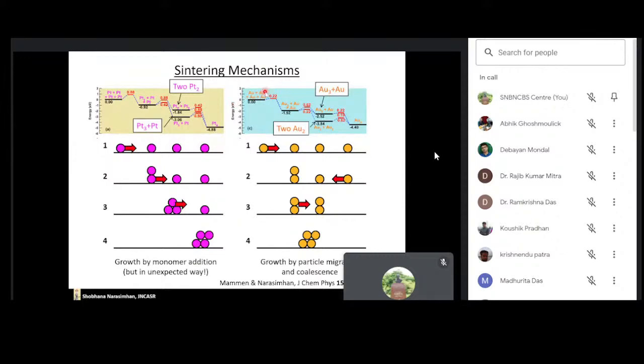And using this data, we can also look at the sintering mechanisms. We can see how the particles coalesce. So we see, for example, that for platinum, the way they coalesce is by one atom being added in a stepwise function. So it goes from 1 to 2 to 3 to 4. But it's an unexpected way. I say unexpected because you would expect that it would be the single atom that would diffuse and get attached to the larger particle. But instead, in the case of platinum, it's the larger cluster that diffuses and gets attached to the single atom. Whereas in gold, there's a different mechanism operating. It's more what we call particle migration and coalescence, where particles migrate and coalesce. So for example, see the contrast between this and this. And so you have growth by particle migration and coalescence.